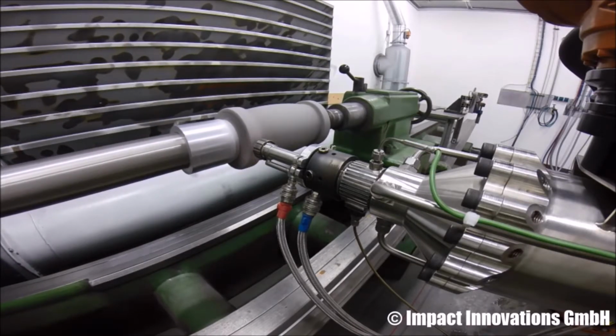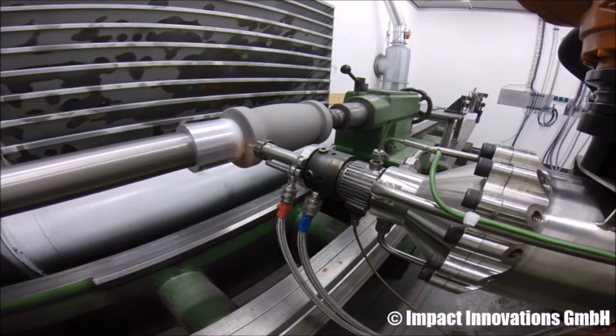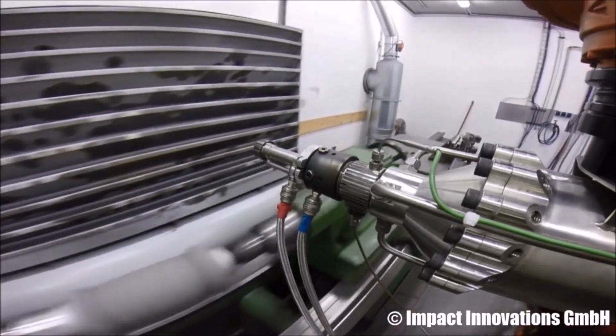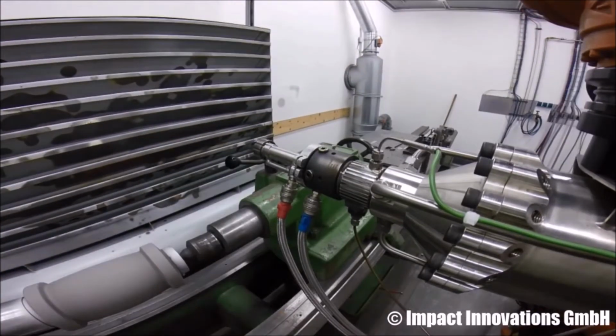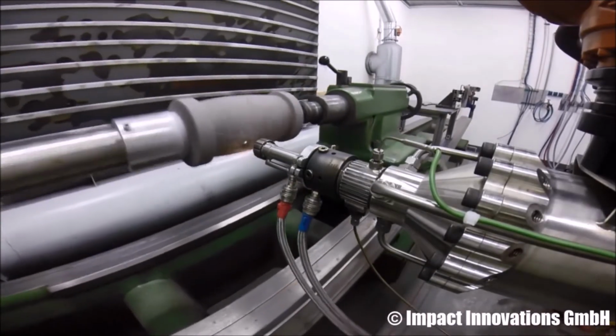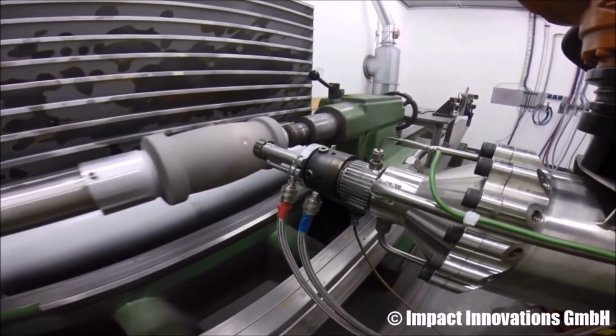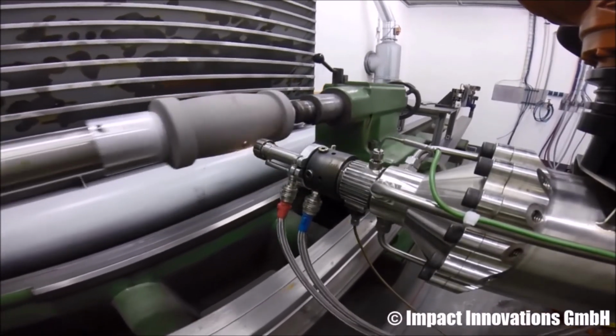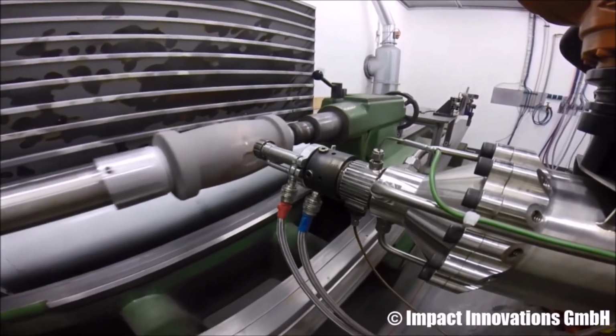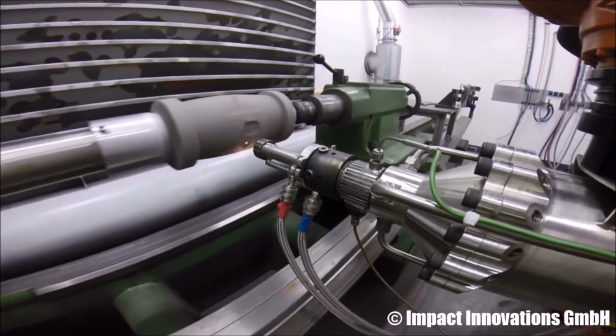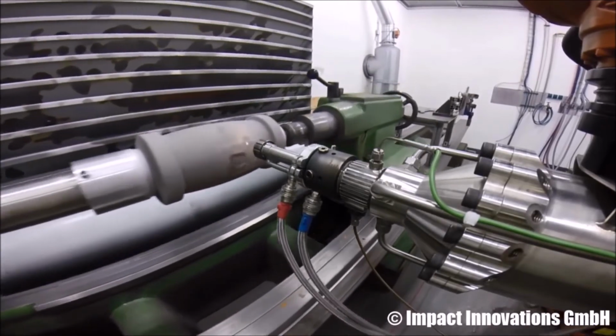At first, the method was used mostly to repair aircraft components made of lightweight alloys. The largest application today is to repair U.S. Army helicopter parts constructed from magnesium alloys. In this case, cold spray is used to rebuild damaged or corroded sections of the part because magnesium cannot be welded. Other popular uses include making thermal barrier coatings and adding corrosion protection layers.